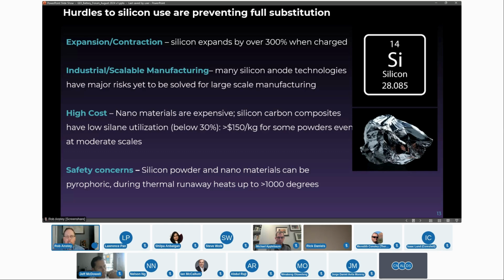And China is starting to make some knockoffs of these materials, and even the knockoffs from China that have lower performance are $110 to $130 a kilogram at metric ton scale. So if even China is selling the material at over $100 a kilogram, that tells you something about the manufacturing.